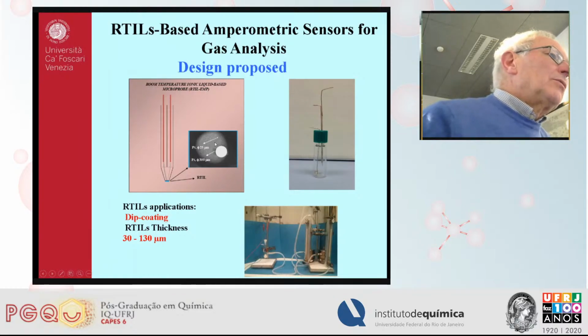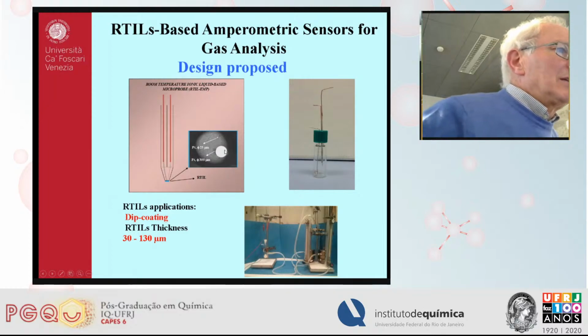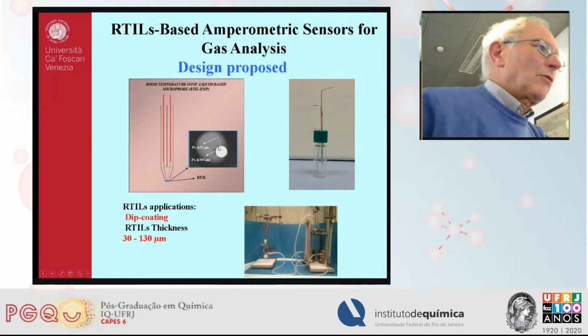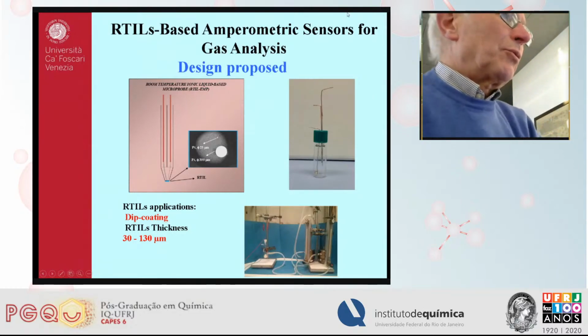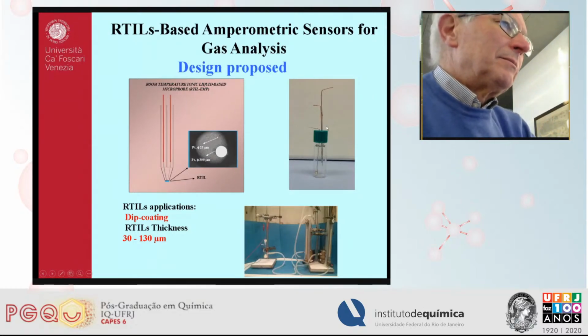So one does not need the 3 electrode systems. To make the contact between these 2 electrodes, a thin layer of room temperature ionic liquid can be applied. And this room temperature ionic liquid can be applied just by dip coating. So the system we realized is this one. This is a system which allows you to make measurements in a gaseous atmosphere.